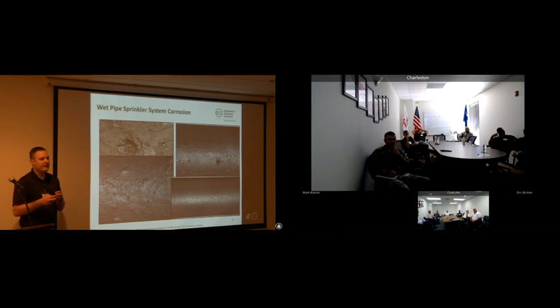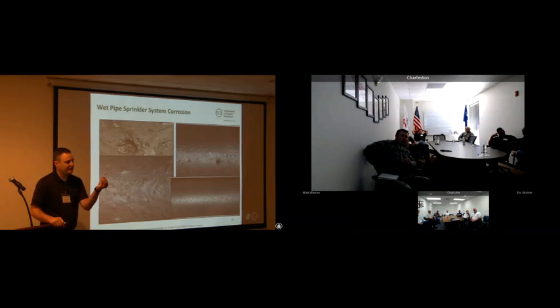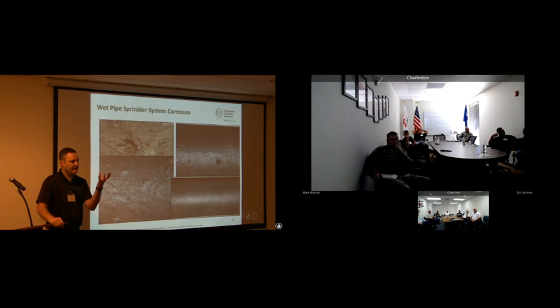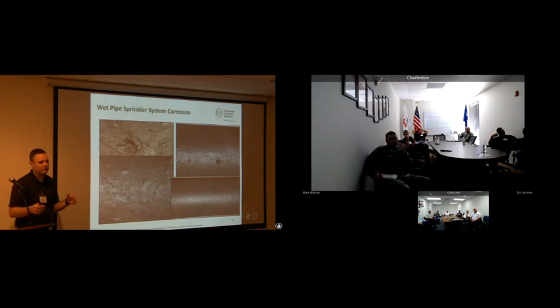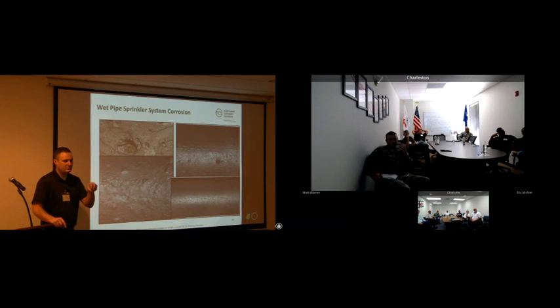If you have MIC, if you have bacteria-based corrosion, what you're going to see is a deep pit, a lot of metal loss, and then as you get out from that point of origination, it's going to have a stair-step function. It's going to kind of look like a canyon was formed. And what that is, the colony adheres to the pipe wall and it starts removing metal. As the colony grows, it's had less time to work on the metal. So that's why you get that stair-step effect. So it's very easy to tell what type of corrosion it is by the metal loss.